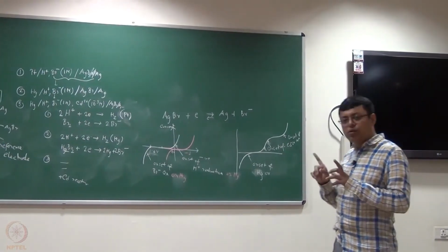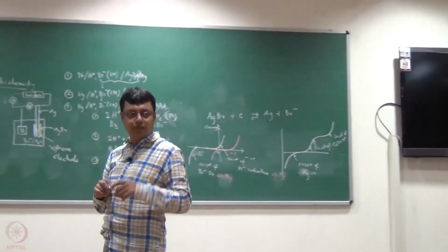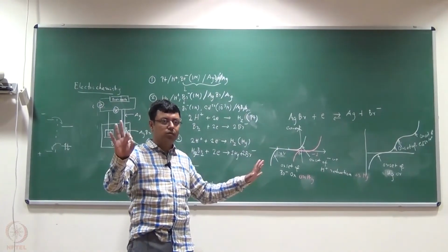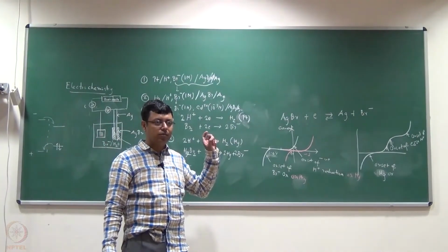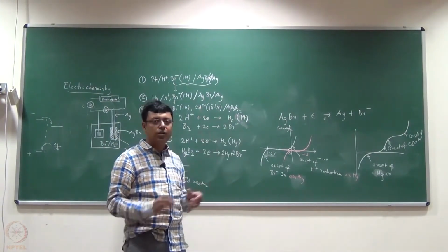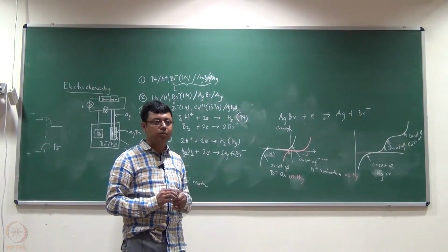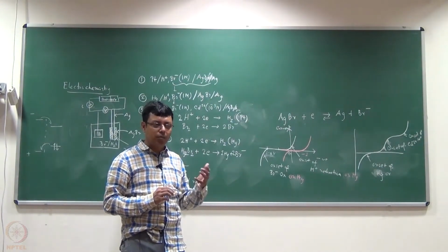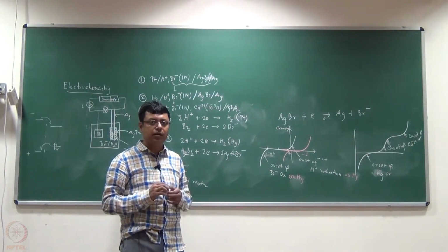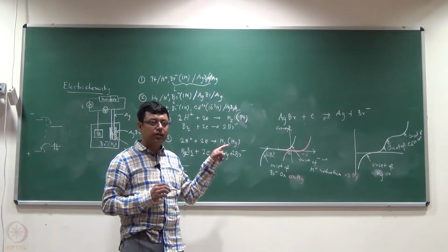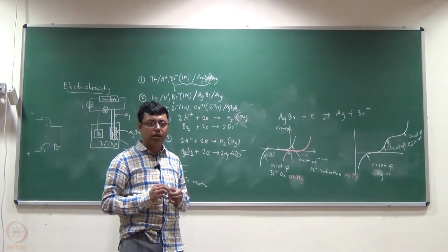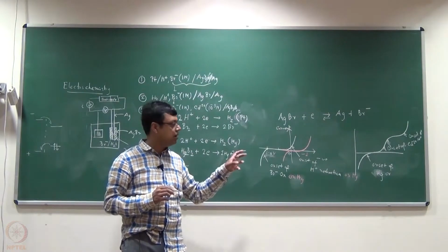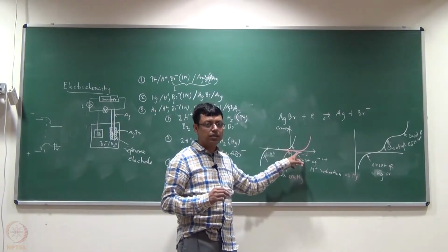Now I actually talked about two different things. One is that I have discrete potential steps. Just two couples. I have the possibilities of hydrogen evolution, or the possibilities of the bromine oxidation reaction, right? Then I said, the moment I switch to mercury, the bromine reaction changes a little bit. It's a different reaction. And the hydrogen thing occurs at a very different potential, because there is a kinetic inertness which is basically not letting this reaction happen.